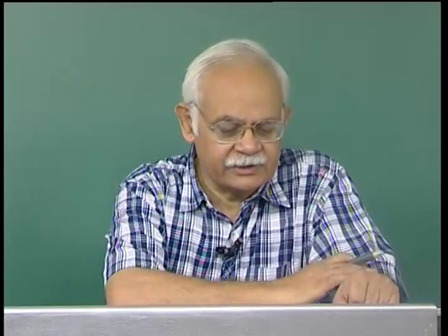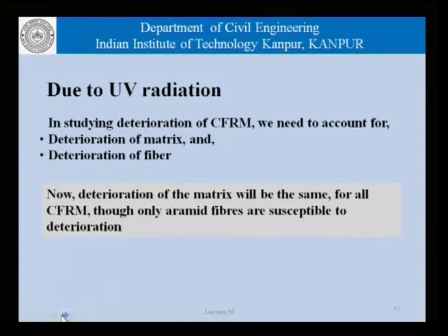As far as ultraviolet radiation is concerned, we have to account for the deterioration in the matrix and the fiber. Most experiments and studies have found that the deterioration in the matrix will be the same, but only for aramid fibers has there been some reported deterioration in the change in strength on account of exposure to ultraviolet rays.